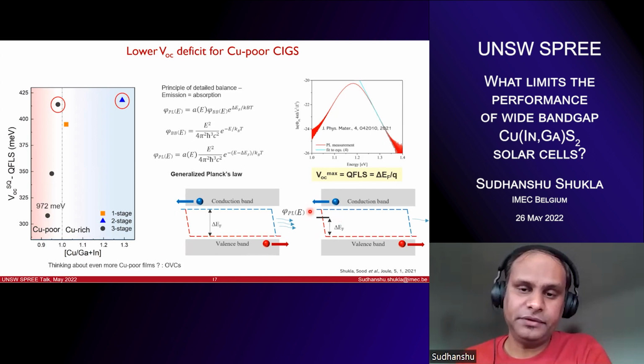Same thing when you have interface recombination, let's say, then the QFLS is going to reduce, because your quasi-Fermi level splitting is limited by the interface recombination. So to check that, we tried to understand what is the difference between a copper poor or, let's say, close to stoichiometric absorber, and what is the difference when we take an absorber which is copper rich. So we compared these two because they had pretty similar quasi-Fermi splitting.